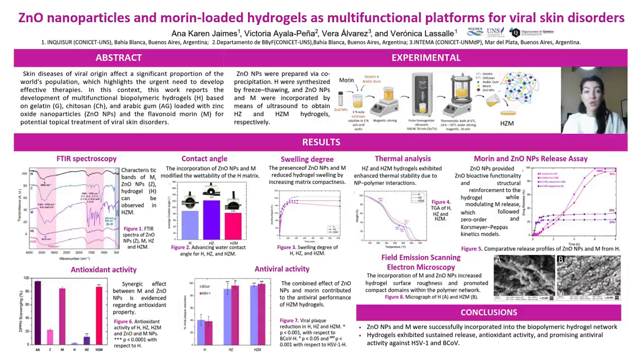Swelling studies showed that all hydrogels exhibited high swelling capacity under simulated skin conditions. However, the incorporation of zinc oxide nanoparticles and Morin reduced the swelling degree due to pore blockage and interaction within the matrix. Thermal analysis demonstrated that zinc oxide nanoparticles improved the structural stability of the hydrogels through nanoparticle-polymer interactions.